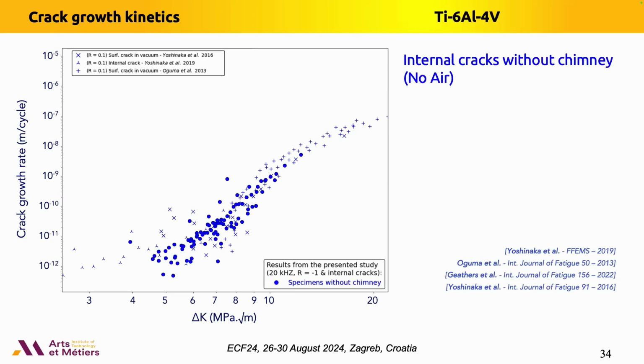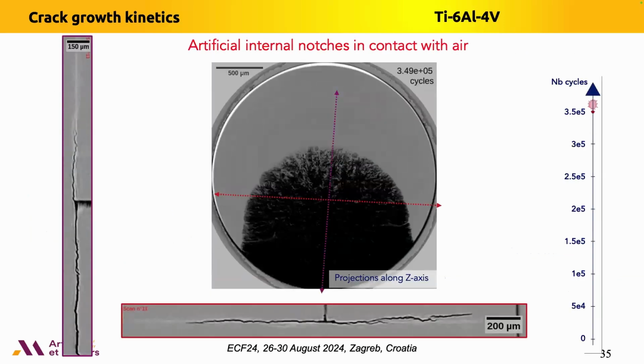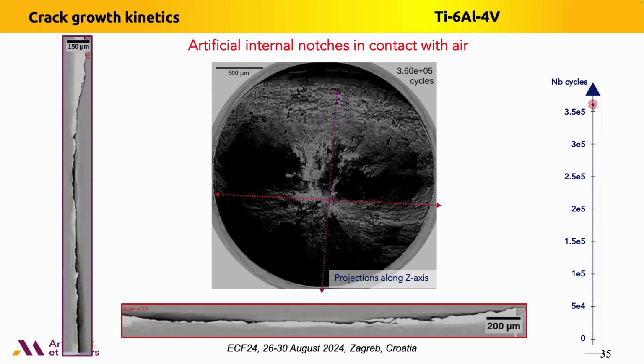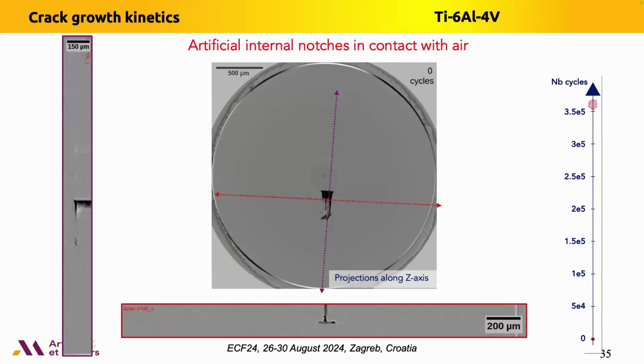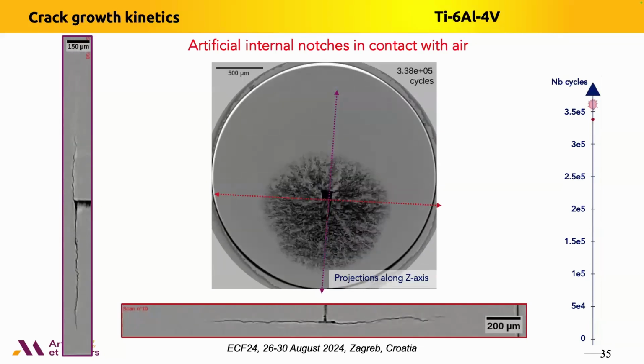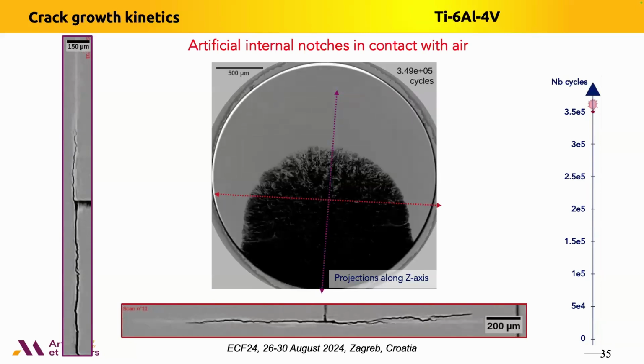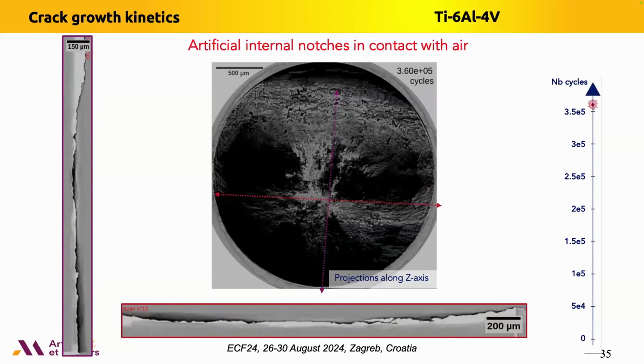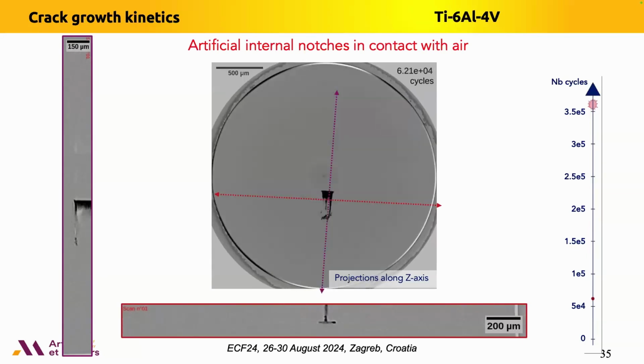Then if we look at the same experiments, but with air inside. So this is the equivalent, of course, on another specimen. You can see here the defect, and you can see the vertical chimney here, and the same here, that allows the air to come inside. And here, only qualitatively, you can see that the crack propagation is much faster. Of course, it depends on how I build the video, but you can see here that the number of cycles going from 0 here to 3.5 10 to the 5 is very quick.